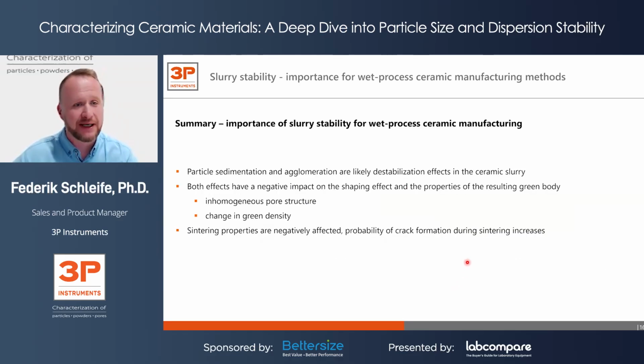So particle sedimentation and agglomeration are likely destabilization effects in ceramic slurries, and you need to try to prevent them, or at least to analyze them. Both effects have a negative impact on the shaping process and the properties of the resulting green body, which leads to an inhomogeneous pore structure and a change in the green density. Last but not least, the sintering properties might be negatively affected by this, and the probability of crack formation during the sintering increases.